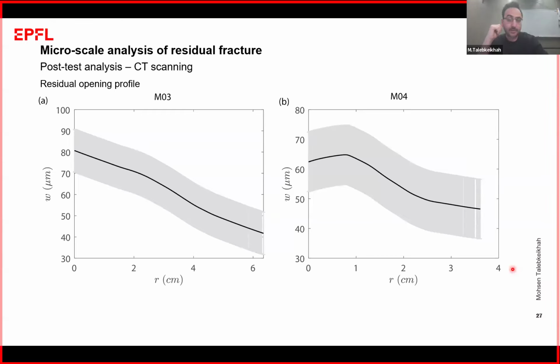First of all, we need a pressure-dependent leak-off model to check, because what we found is that it is not observing the LEFM that we have normally, and we cannot use those techniques because we can see a huge backstress of about 20 megapascal occurring during our experiment, and this 20 megapascal is the deviation from the normal LEFM equations that we have normally with the Carter leak-off assumption.